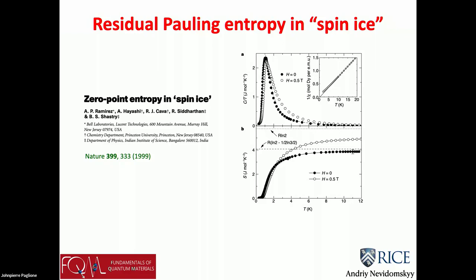So what they pointed out is that if you compute the specific heat in this material, you subtract the noise, and you compute the entropy by integrating C over T, you find that the entropy recovered is this dashed line, which is actually not R log 2, which is what you would expect if it was a full entropy per moment, but instead it's less. And the difference is precisely the residual entropy that Linus Pauling computed, that remains sort of quenched, unsatisfied.